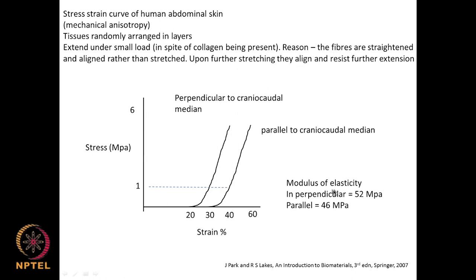The modulus of elasticity (Young's modulus) in the perpendicular direction is 52 megapascal, and in the parallel direction it is 46 megapascal — both are very different. So depending upon how the tension is applied, whether perpendicular or parallel, it will exhibit two different graphs as shown.